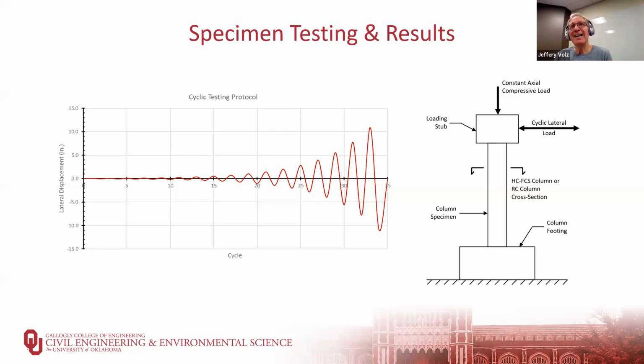Based on calculations, we wanted to make sure that we didn't push it too far for the initial displacement, but we wouldn't want too small of a displacement or it would take forever to run the test. And so we arrived at a displacement of 0.05 inches for the initial displacement. And that was expected to require a lateral load of about 2,000 to 2,500 pounds to get to that displacement. So that was our starting point. Our ending point was a displacement of almost 11 inches, the 10.89 inches. And all of the columns we failed before or when we got to that point.